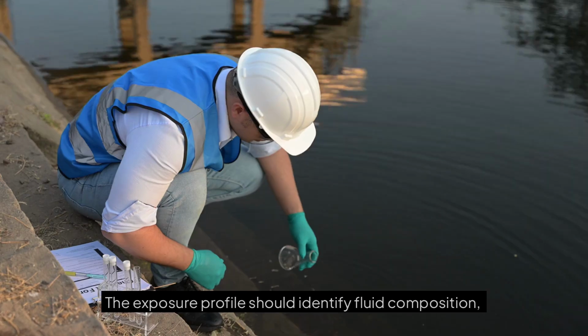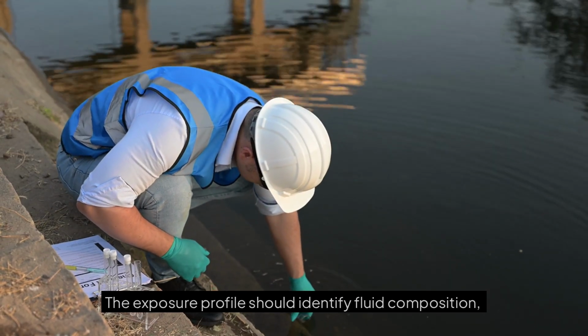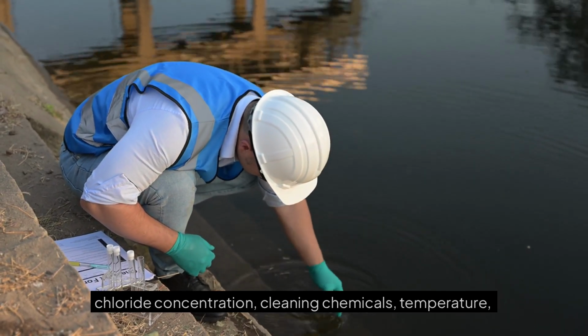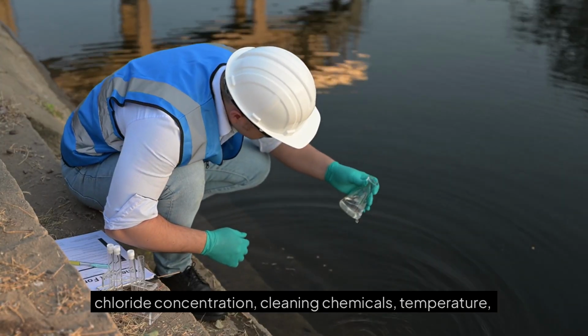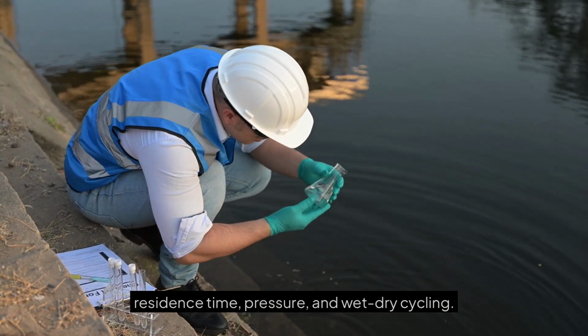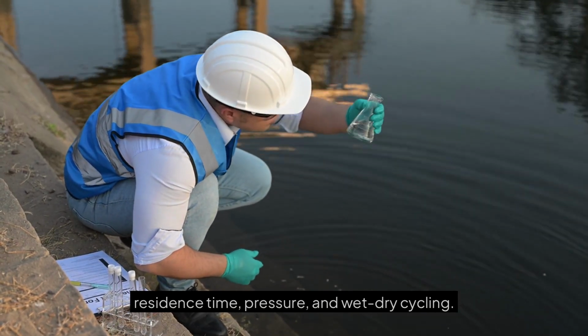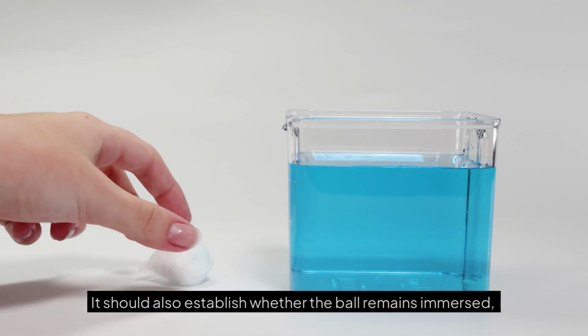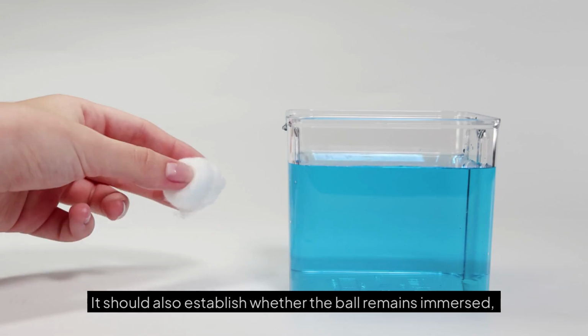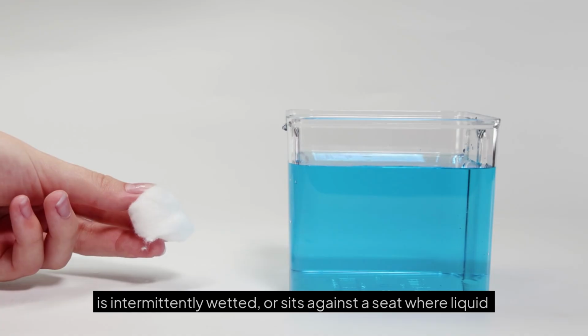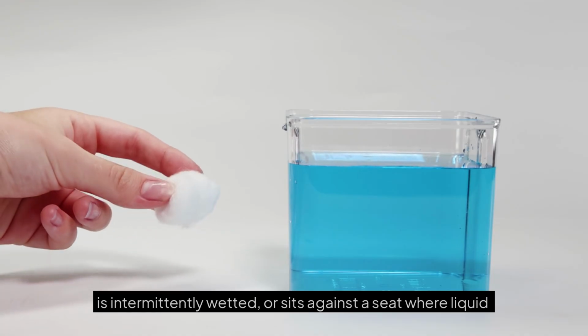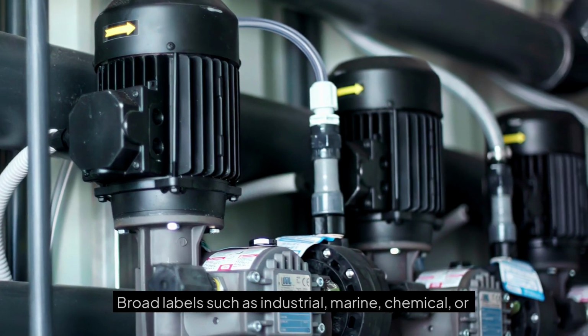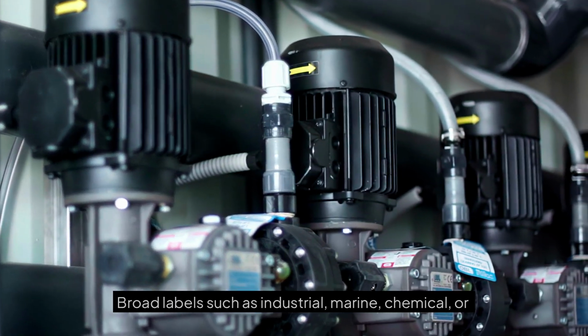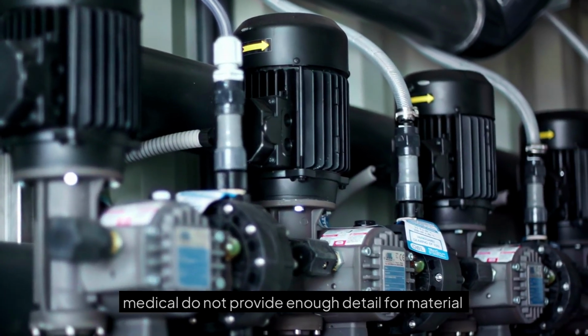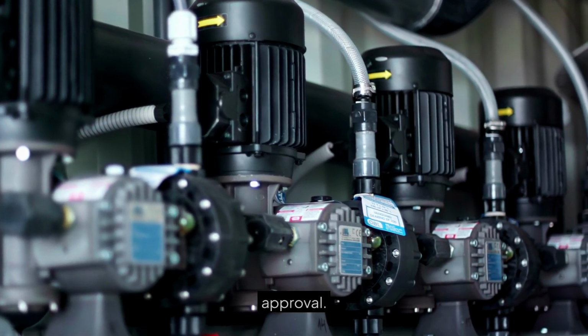The exposure profile should identify fluid composition, chloride concentration, cleaning chemicals, temperature, residence time, pressure, and wet-dry cycling. It should also establish whether the ball remains immersed, is intermittently wetted, or sits against a seat where liquid can be trapped. Broad labels such as industrial, marine, chemical, or medical do not provide enough detail for material approval.